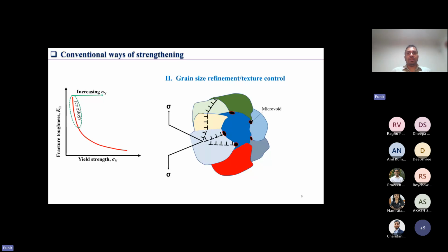And in comparison, if you have grain boundaries which are high angle and they don't allow transmission of dislocations across the grain boundary, or activation of a newer slip system in the neighboring grain, in those cases you might be nucleating microvoids on the grain boundary. So there are two possibilities in this case. You can in some cases improve the yield strength without significantly affecting the fracture resistance, but in some cases you will be affecting the fracture resistance. Also, it's very difficult to control the characteristics of the grain boundaries through the existing metallic processing we have. So that's another challenge